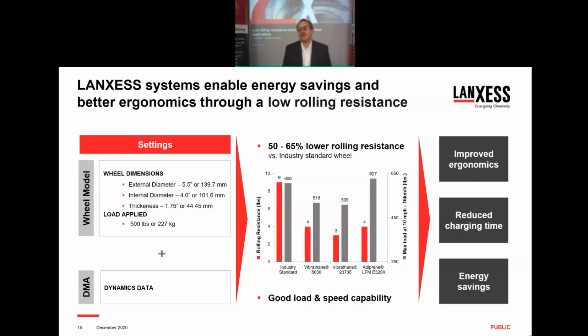And then when we look over to the right-hand side here, the Adiprene LFM E320, again, this was the material that combines and bridges that gap between the ester or the caprolactone and the ether. And what you see here is significantly higher load capability and very good rolling resistance compared to the industry standard. And just for comment, all of these materials are roughly 75 to 80 Shore A in terms of the hardness, so there isn't a huge difference in hardness. Actually, the highest hardness one here is the 8030, at 80 Shore A. The rest of them are at 75 A.